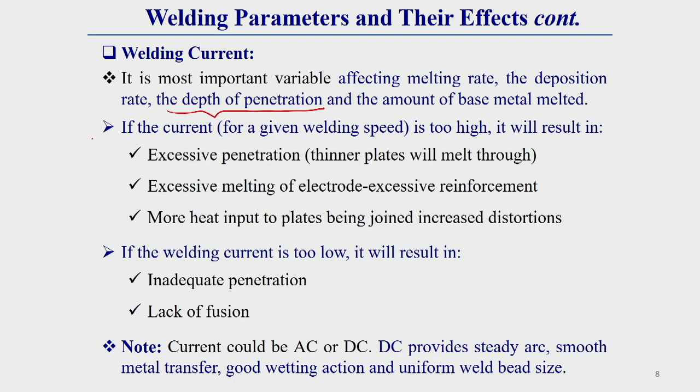So if the current is high, this turbulence effect and all these things increase. Due to this turbulence or axial force effect, more penetration takes place. And as I have already discussed, the heat energy is also directly proportional to the square of the current. So if the current is more, then the heat energy will be more. More heat energy means more material will be melted. That means the deposition rate will also increase.